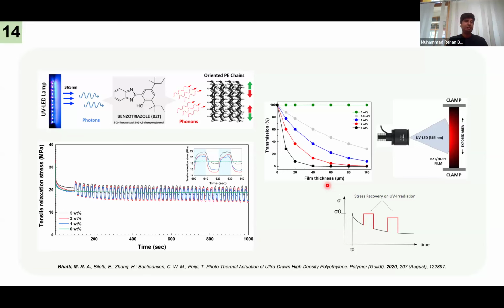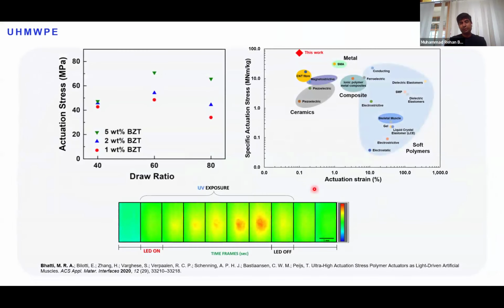But there is a limitation for high-density polyethylene. When the film thickness is higher, the light cannot pass through the film completely, thus creating a thermal gradient, which does not allow us to exploit the full potential of the BZT within there. So in the next phase of our research, we used ultra high molecular weight polyethylene,